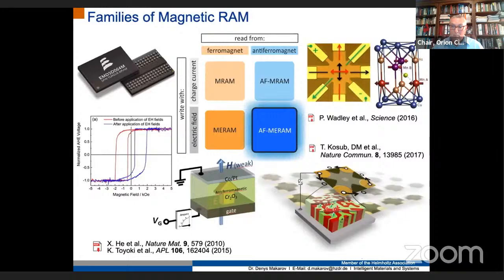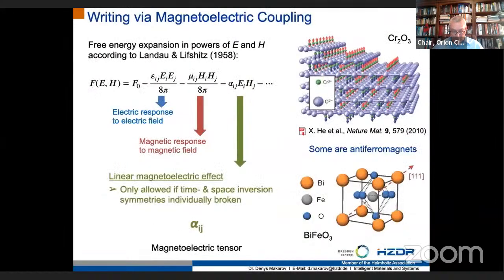In our work, we removed the ferromagnet from the stack and ended up with antiferromagnetic magnetoelectric random access memory, where the memory cell contains only chromium oxide as a magnetoelectric insulator, which is interfaced with platinum readout electrode to access the magnetic state of the antiferromagnet. As many other groups in the community, we work with chromium oxide, which is the only uniaxial antiferromagnet which has magnetoelectric effect at room temperature.